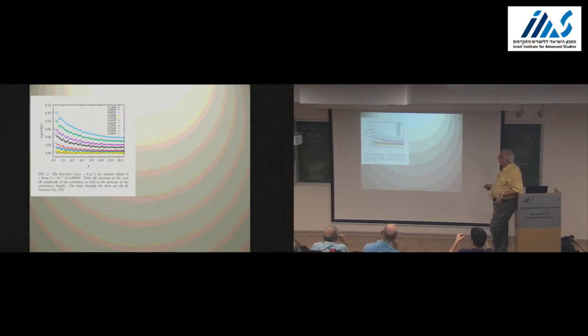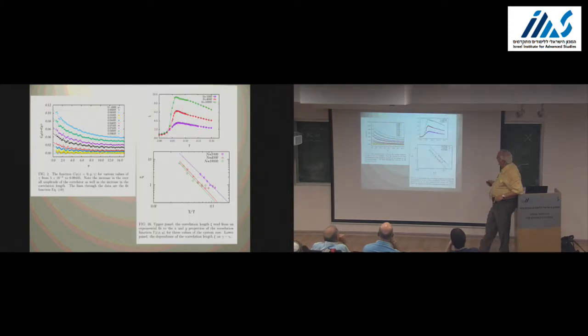So, for example, I'll show you here the replicon, a cut through the replicon. This is in a two-dimensional system. So you look at x equals 0 as a function of y. This is when you're far away from criticality, from the spinodal criticality. And then the correlation length is increasing. Here you see the correlation length measured from this as a function of the system size. So here it doesn't grow that much, grows more, and it's going to diverge in the thermodynamic limit.